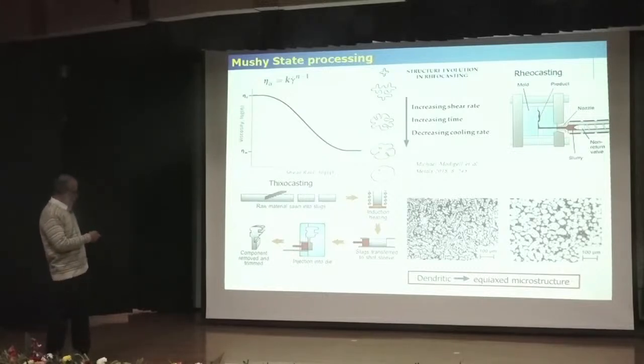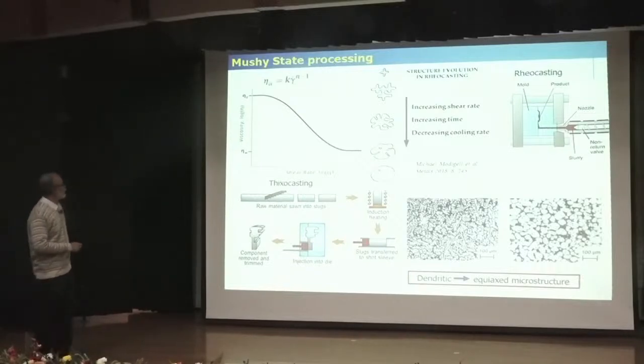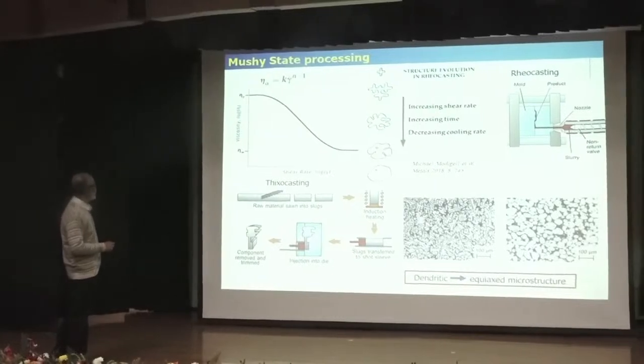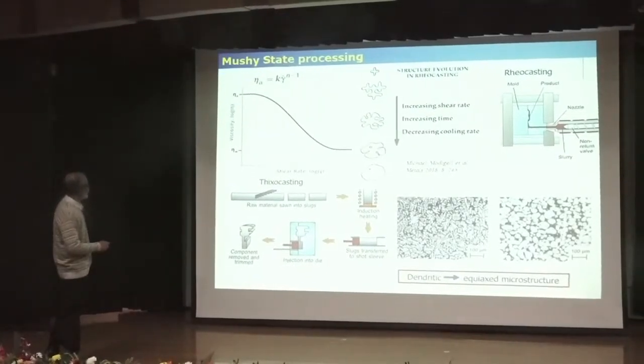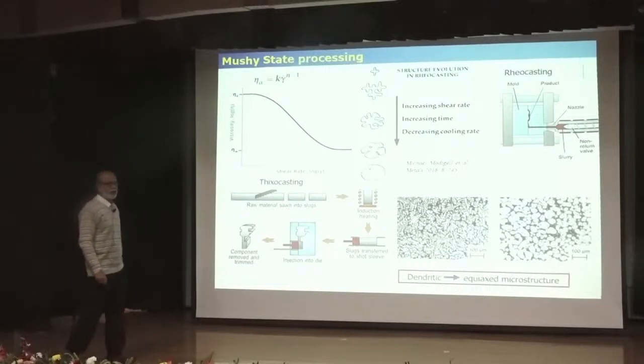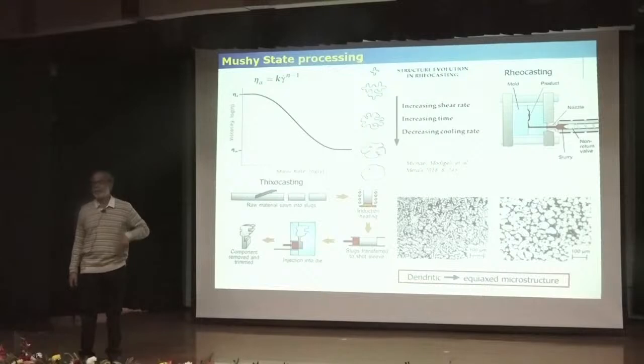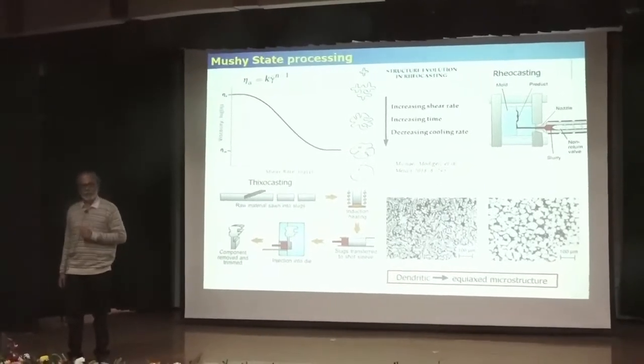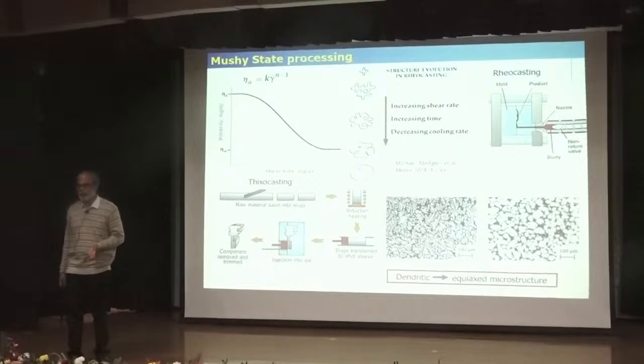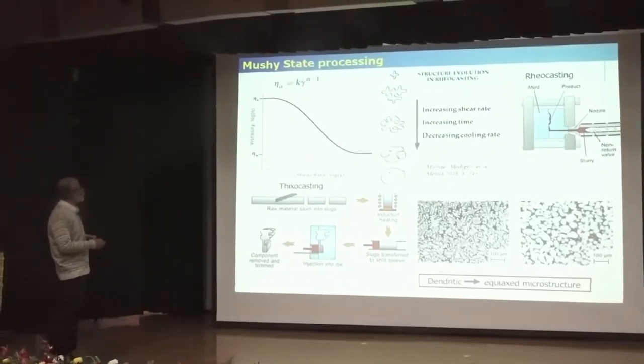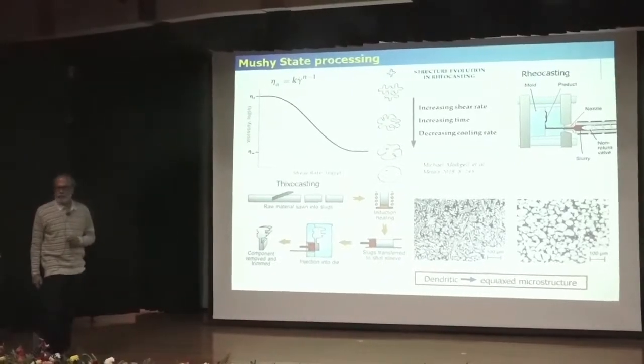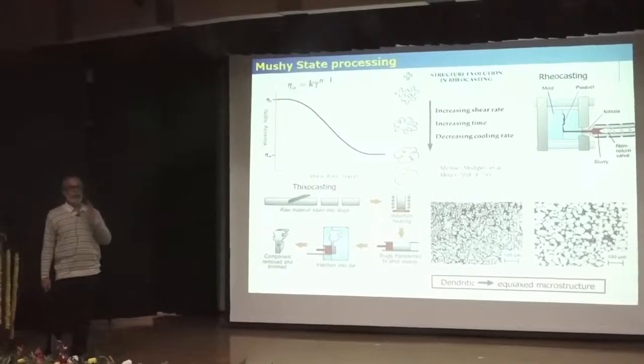And it was found that application of shear stress reduces the viscosity, shear rate reduces the viscosity following this non-Newtonian equation, where K is a consistency parameter, n is the flow coefficient, and gamma dot is the strain rate. So they could find a way out to reduce the viscosity in the semi-solid stage by application of shear. Not only that, application of shear fragments the dendrite, and these fragmented dendrites provide the nucleation sites for fresh grains. So they could transform the dendritic microstructure to equiaxed microstructure,